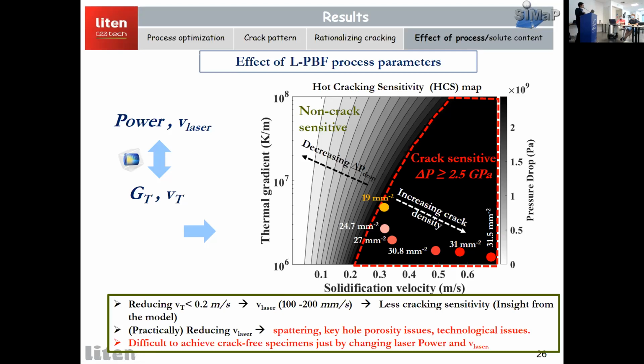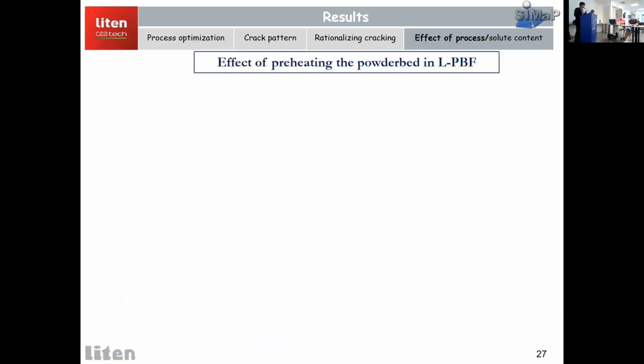But practically speaking, these lower speeds can induce different problems like spattering and keyhole porosities, and there might be other technological issues. So in short, it's very difficult to achieve a crack-free specimen just by playing with laser powers and laser speeds.